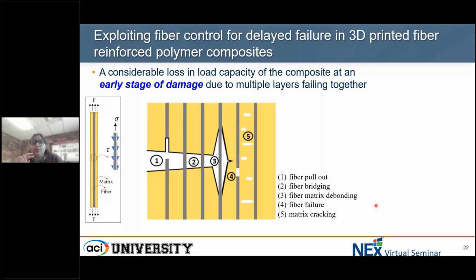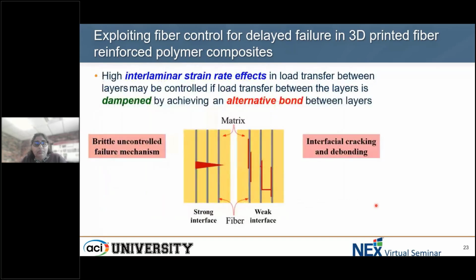But the problem here, though, is that shear transfer, if dampened, also affects its mechanical properties, which is strength and other kind of properties. So considering this, if you see a brittle uncontrolled failure mechanism in a strong interface, whereas an interfacial cracking or a debonding in a weak interface, an alternative kind of bond needs to be established. And we are talking about 3D printing here, which is mostly like a continuous process. So how do we establish this alternative bond between the layers?